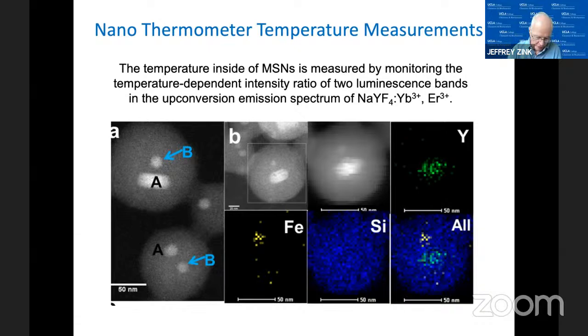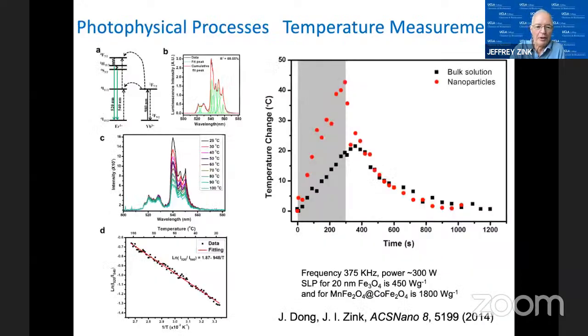So for these particular studies, we took a look at the temperature. So we made a little nano thermometer. It's a yttrium fluoride doped system. And we're able to put that nano thermometer in the same nanoparticle as the heater, the superparamagnetic particle. So we were able to make silica particles that contain both of these components, the heating component, the superparamagnetic particle, and the optical thermometer. And we characterize, and you can see that we have the iron and we have these yttrium in the different places. The particle, we do have these dual core shell particles.